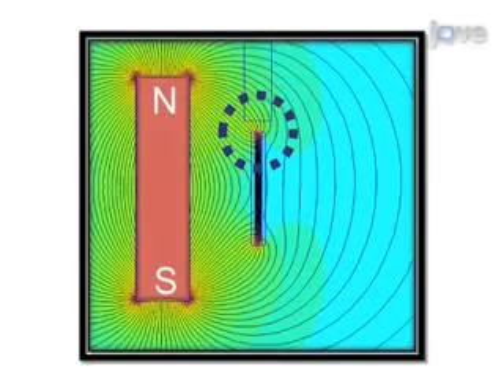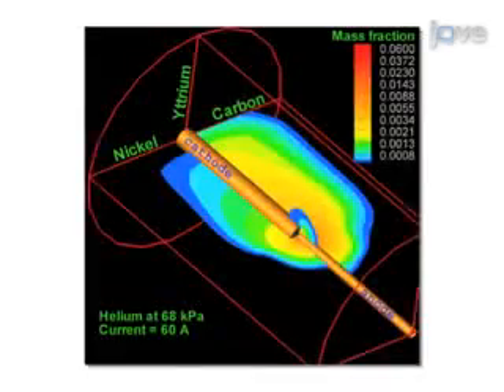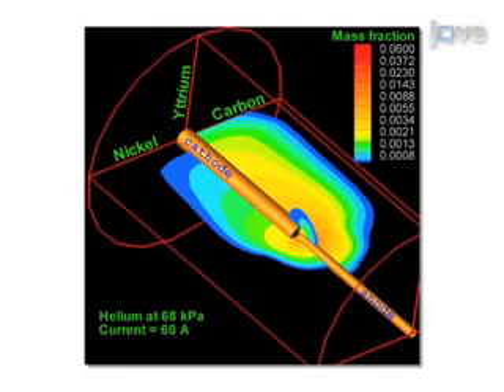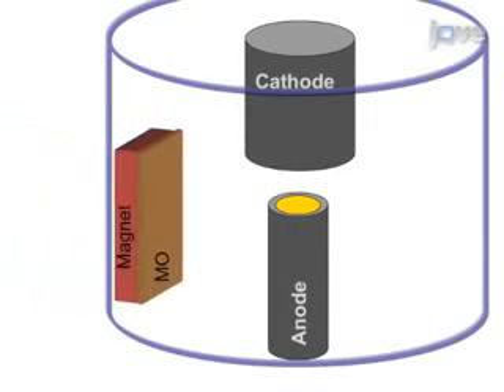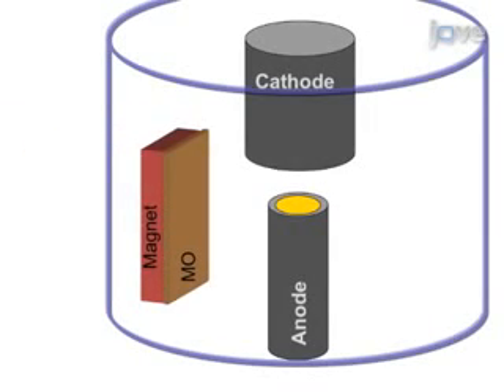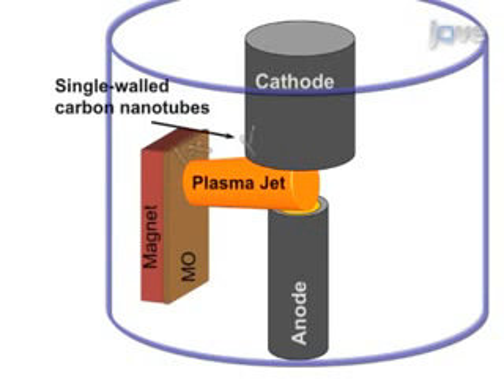Then, numerical simulations presenting the distribution of the magnetic field and species particles are used to provide the detailed information about the location of synthesis. Then, the magnet and the molybdenum sheet, which functions as a substrate, are installed according to the simulation results, and the arc discharge between the electrodes is initiated. A plasma jet is formed, and it deposits single-walled carbon nanotubes and graphene on the surface of the molybdenum sheet.